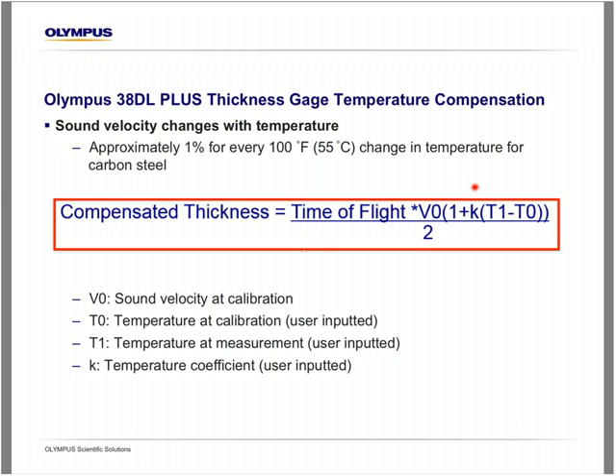So what the temperature compensation feature allows the user to do is enter the temperature at calibration, which is usually an ambient temperature, the temperature at the measurement, which is the hot pipe, the elevated temperature application that you're measuring, and the K coefficient for the material being measured. By default, the K value is for carbon steel, because typically that's what users are measuring. But you do have the ability to adjust that K value if you are measuring something other than carbon steel. So again, this allows for a more accurate thickness reading since you're using the adjusted sound velocity. And also it's much easier than trying to calibrate on a hot test block to compensate for that velocity change.